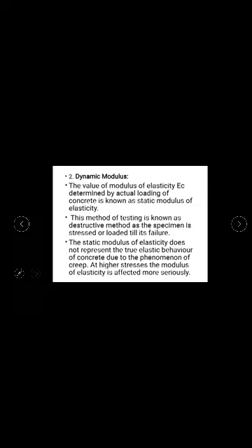In reinforced concrete structures, it is used to determine the stresses developed in simple elements, and also to determine the moments, deflections, and stresses. All this can be found out only when the Young's modulus is known. The dynamic modulus is used to determine the relative durability of concrete when exposed to severe climatic conditions. As the dynamic modulus of concrete changes with the quality of concrete, this method is very useful to determine the quality of concrete when it is subjected to alternate freezing and thawing.